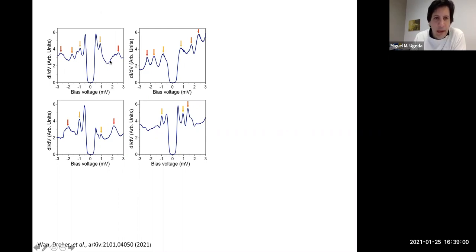see without the need of any statistical analysis is that in general they show up in pairs for empty states and filled states, and they are in general quite equidistant in energy, not totally, but sometimes we don't see some of them. Sometimes they appear symmetric, sometimes not. Here in this case, for example, there is just one that we can clearly distinguish. On this side, there is two, but that's a feature that we see very common.